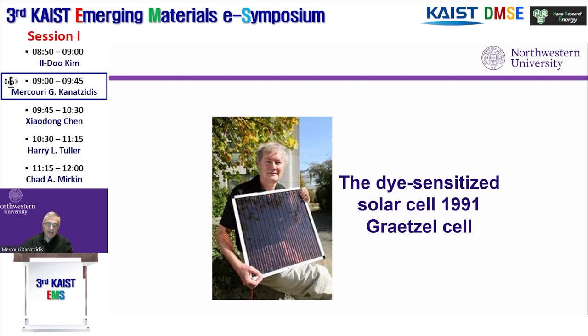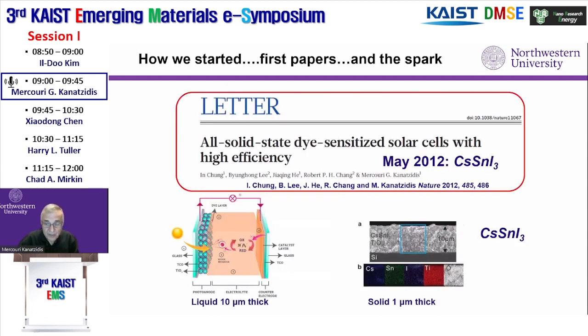The problem was that because it's a solution device, the device actually has solvent in it. It was not very stable, and it would decompose within months. And so no one was happy with this, and everybody was clamoring for a solid-state device that would solve the stability problem. And so our work was inspired by that, and therefore we wouldn't have done what we did if it wasn't for the Gratzel cell. So in saying that, we published this paper in May of 2012, reporting an all solid-state dye-sensitized cell based on the perovskite material.